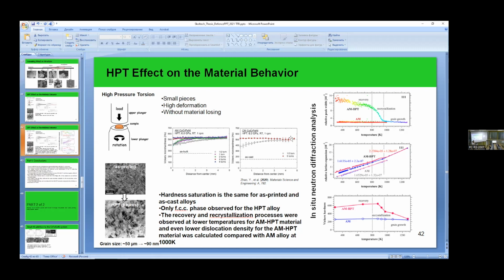And we see it's according even for the micro hardness response. For the first stage, this TEM image was taken in the middle of the radius, but generally we conclude that it's approximately the same grain observation for the whole sample, since we observed the same micro hardness response. So you saw micro hardness the same along the radius? Yes, yes, but the images we presented only on the half of the radius.